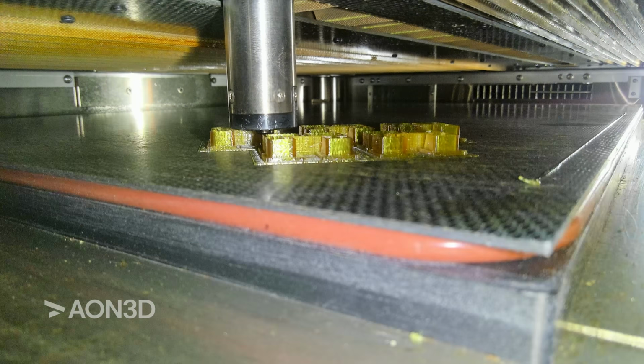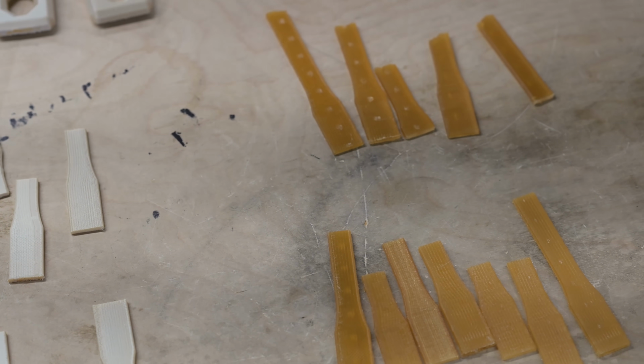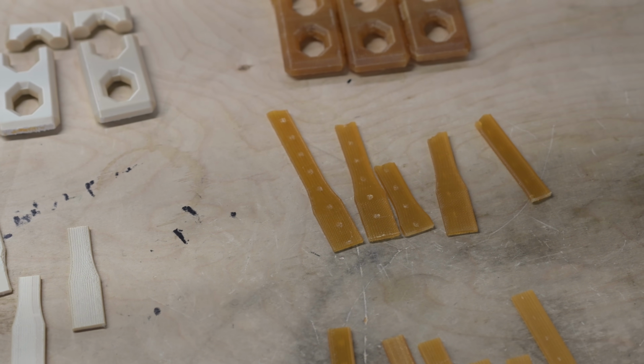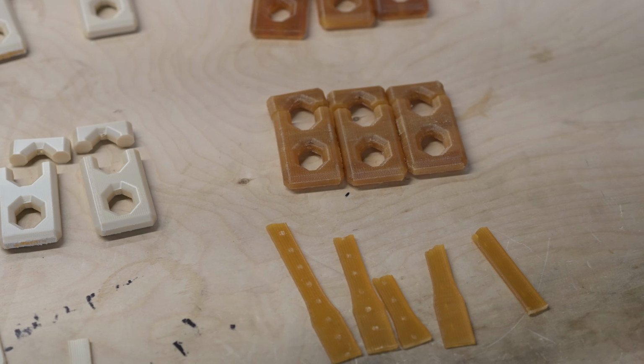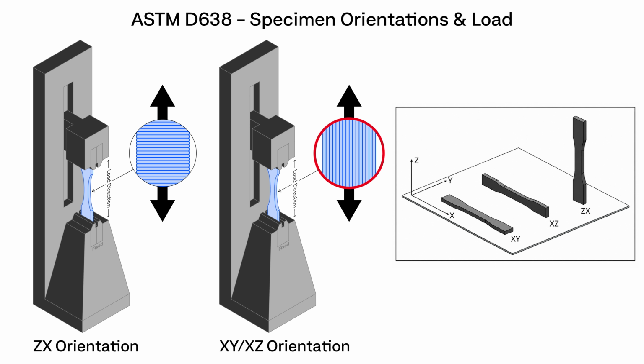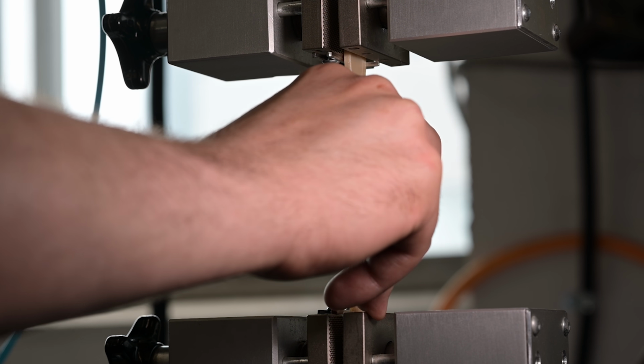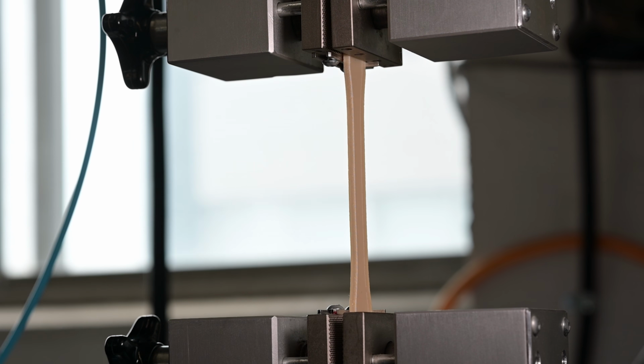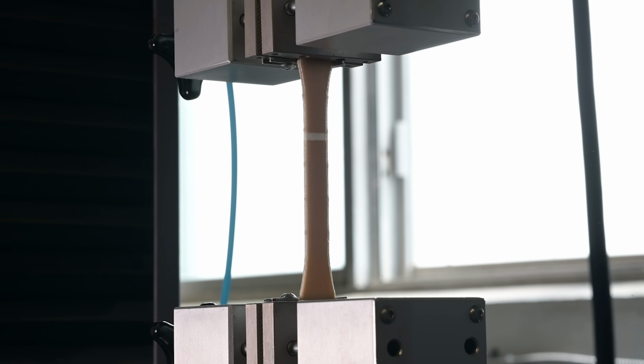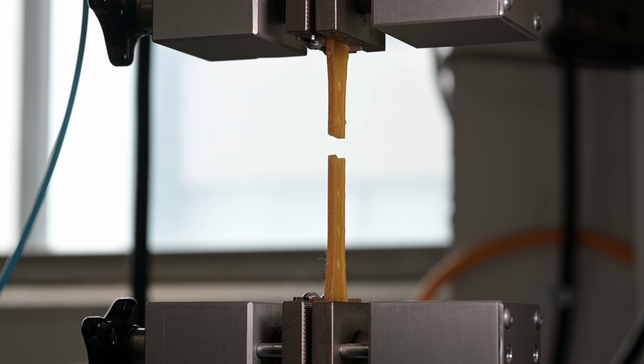So the next question becomes, how much of your mechanical performance is compromised by printing in a 120C chamber? To answer that, we printed ZX tensile bars 5 at a time to replicate the layer times and thermal conditions of a real part. Unlike XY specimens where the load is primarily carried by continuous extruded beads, ZX specimens transfer that load across hundreds of deposited layers. Rather than measuring the polymer's bulk strength, ZX testing evaluates how effectively the printing process manufactured the part.